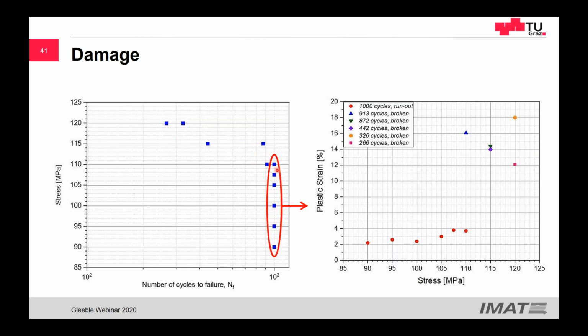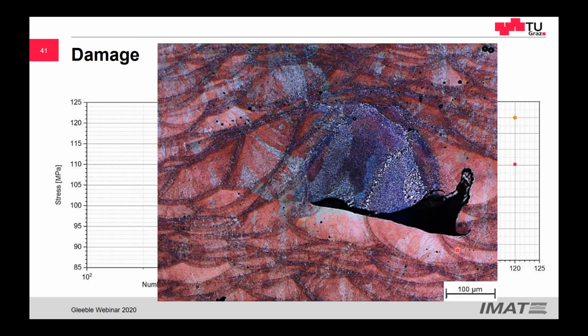And these were ongoing, so this didn't break. We also relate this damage to the plastic strain. So we could see that at very low stresses, the plastic strain is very small until we reach a peak, and that is where our material breaks. And here there are some lines where you can see close to the fracture. You can see that the material fails where we have a large amount of heterogeneities. So of course, these kinds of materials are not easy to test because they are very heterogeneous. But even so, we could see that we could simulate this testing, this thermal cycling, and get some information out of it.